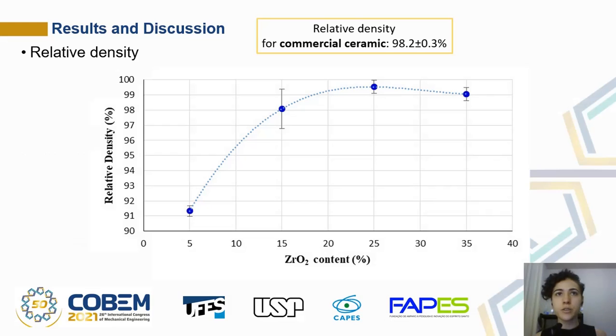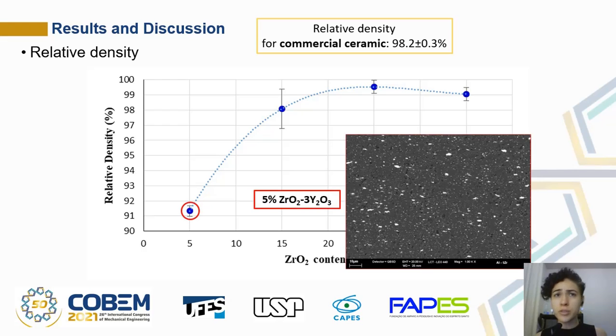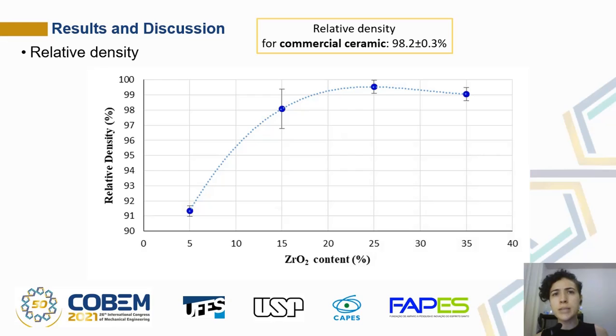This graphic shows the relative density results for the four volumetric zirconia fractions. The porosity observed in the micrograph is related to the mean relative density value for the 5% zirconia sample. The results show an increase in the relative density with increasing zirconia content, and considering mean density values, full densification can be regarded from the 15% of zirconia volume fraction.